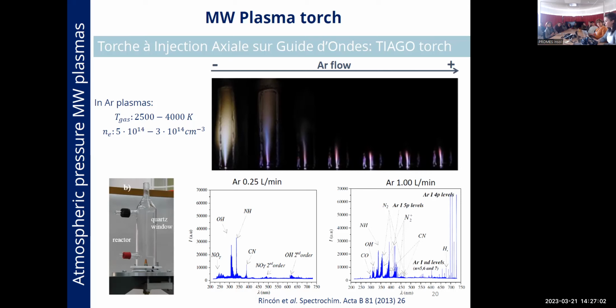What does it mean? It means that when we increase the argon flow, we are limiting the entrance of air from the surroundings, and the nitrogen and the oxygen from the air have a lesser impact on the plasma itself. You can see here, for example, in this emission spectrum, generated with the smaller argon flow, that there are no atomic emission lines of argon or nitrogen, but only molecular ones. Even if the plasma is running in argon, there is no argon in the spectrum, but molecules that come from a mixture of argon and nitrogen.